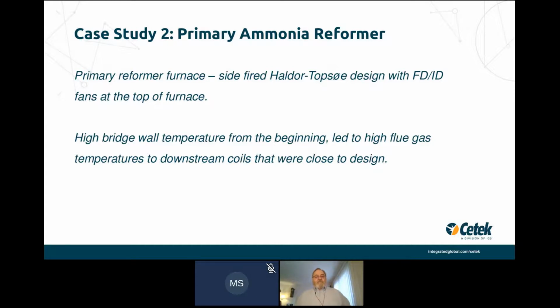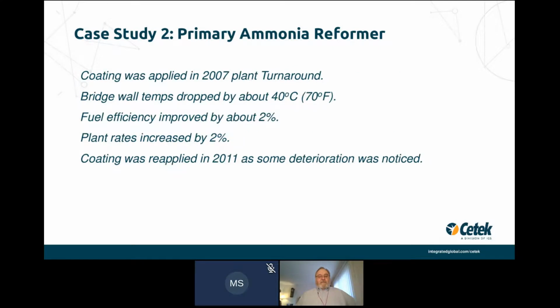So another case study here. This was a Haldor Topsoe unit. They'd had high bridge wall temperatures from the beginning, or high flue gas temperatures to the downstream coils that were actually close to design. We applied the ceramic coating in 2007 plant turnaround. The bridge wall temperatures dropped by about 40 degrees C or 70 degrees Fahrenheit. And the fuel efficiency was improved overall by about 2%. They found that they could also use the benefit to increase the production rate by 2% as they required.